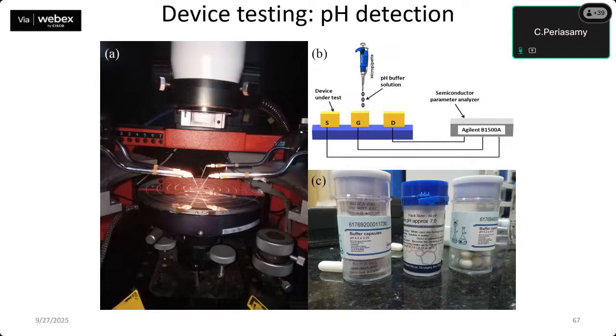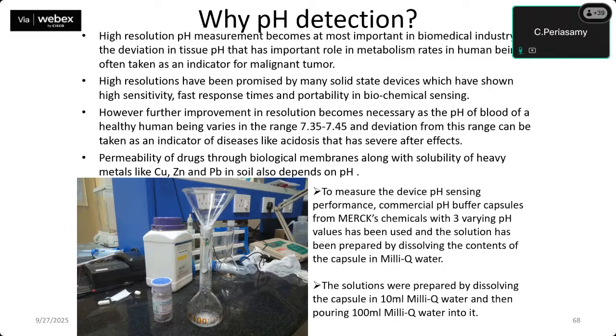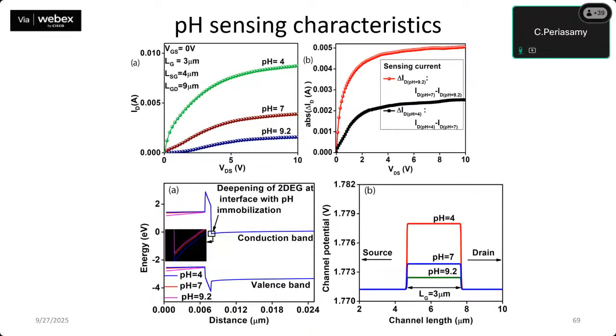So this is the experimental setup we have used to test the pH range present in the sample. We have chosen different pH solutions to test whether the fabricated structure is suitable to sense the pH range. So we have chosen pH values 9.2, 7 and 4, which cover both acidic and base. We exposed these selected pH values on the fabricated structure, and we measured the corresponding output characteristics.